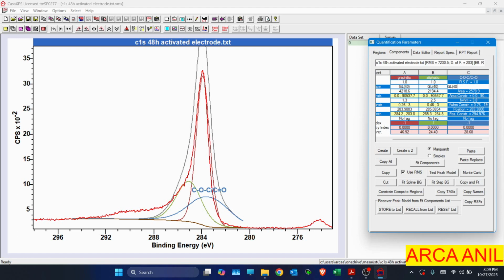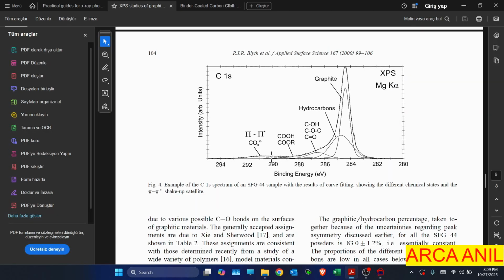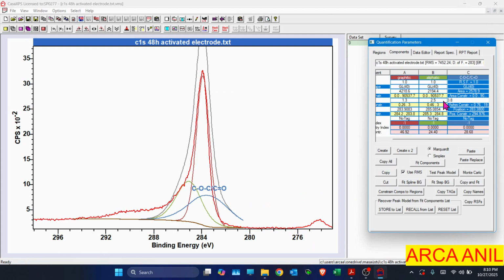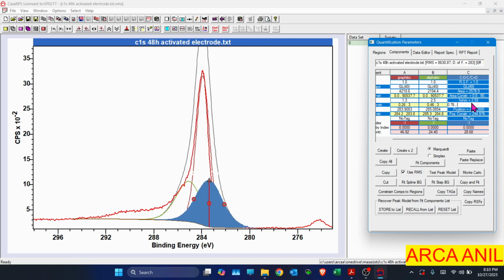I will again use GL40. Full width half maximum. This is also a broad peak. As you see, it's pretty broad, maybe more than 2. So I don't know. Maybe it should be around 2 or 2.5. And constraint can be between 0 to 3.1. I think this should be good enough. And the position should be around 286, maybe 0.5.